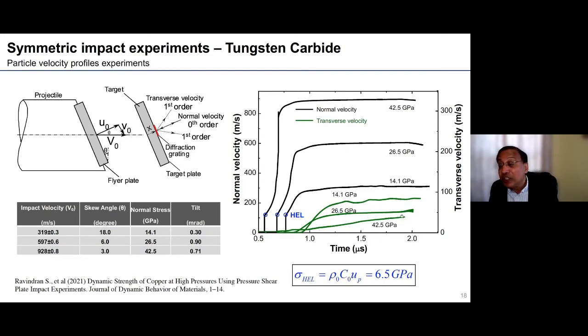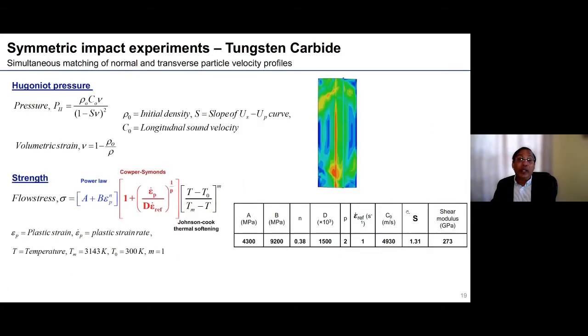So the transverse velocities themselves range from, say, about 40 meters per second to about 90 meters per second. So this is the range of the transverse velocities. And you can see this is directly giving you a measure of the flow strength of the tungsten carbide. So this is how we are able to calibrate the tungsten carbide. Now let me show you the calibration model for this.